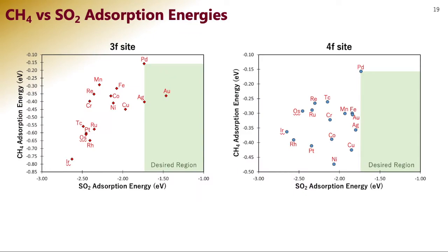In the precursor-mediated mechanism for methane activation, CH4 first adsorbs on the surface, and the resulting molecularly adsorbed state serves as a precursor for C-H bond cleavage. Thus, the adsorption energy of CH4 can be used as an approximate descriptor of activity for methane activation. That is, the desired catalyst should promote a stronger adsorption of CH4 compared to the pure PdO(101) surface.